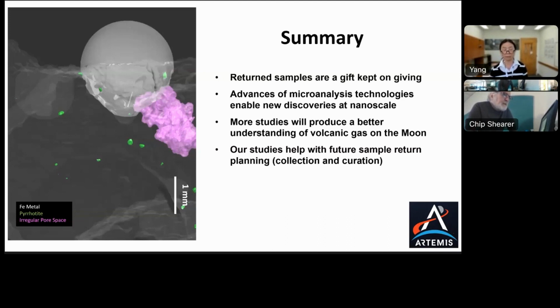So both are possible, viable processes. Either copper was condensed early by volcanic gas and then remobilized and reconcentrated on the vesicle walls, or it can be somehow extracted from the iron sulfide part of the sulfide melt. The sulfide we see in the rock matrix, where on the fracture surface we see those copper sulfides, appears to be suggesting there's some kind of mobility of whatever deposited the copper sulfide. So, there are just not enough experiments done to help us say, hey, it has to be this process.